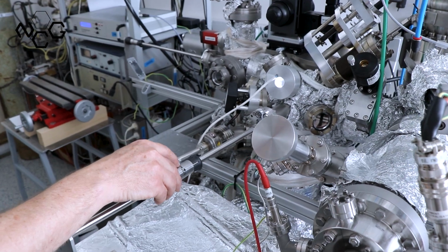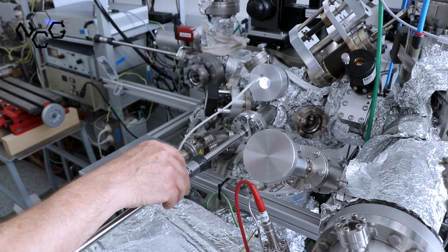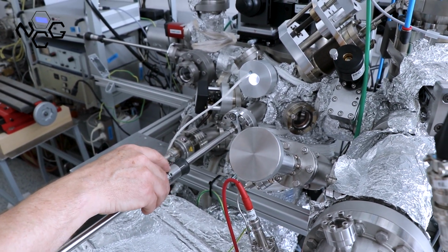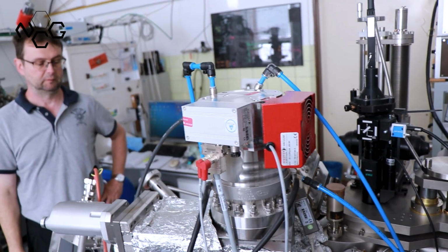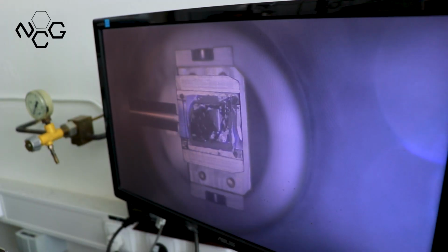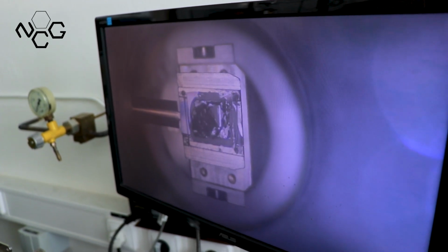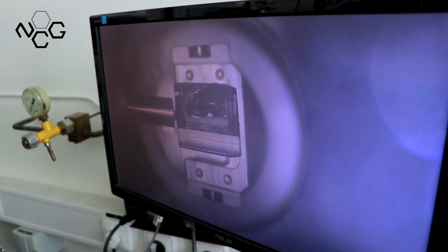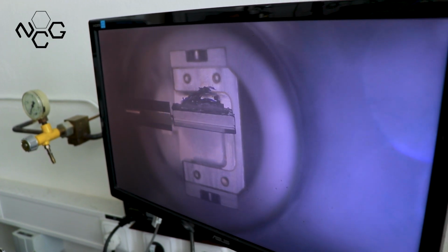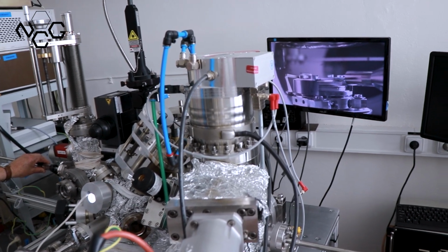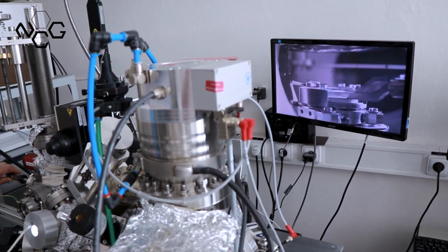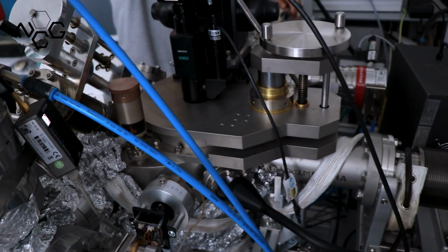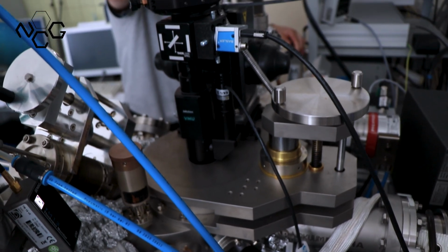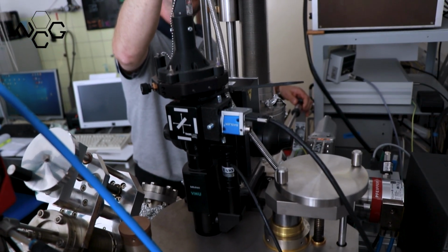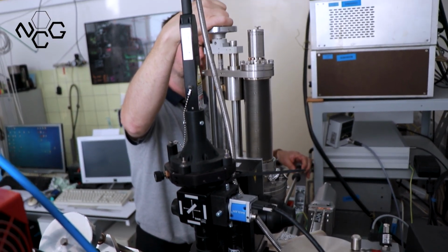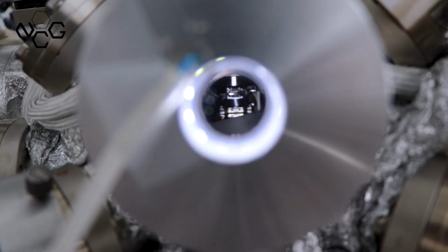Therefore, we have inside the chamber manipulators for sample movement, a heating stage, an arm to approach it, and a metal evaporator. Thanks to all these components, we can cleave a 3D crystal using tape and from the tape exfoliate monolayers on freshly prepared adhesive metallic layers. The first inspection of the prepared samples can be done in situ using an optical microscope and a simple Raman spectrometer. The machine is versatile because we can easily change crystal, substrate or metal.